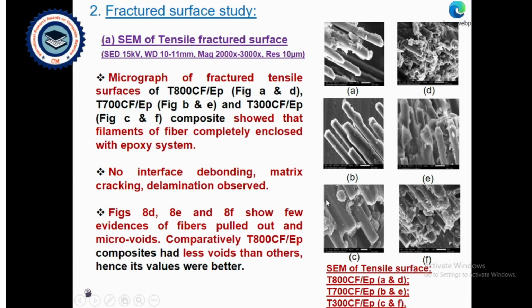were observed. However, there is definitely a difference in various mechanical properties, and we can see that there will be differences. Maybe small voids may be there comparatively. There may be lesser voids in some of them and higher voids in others. Figures D, E, and F show few evidence of fiber pullout and micro voids. The T800 composite has fewer voids than others, hence it showed higher values.